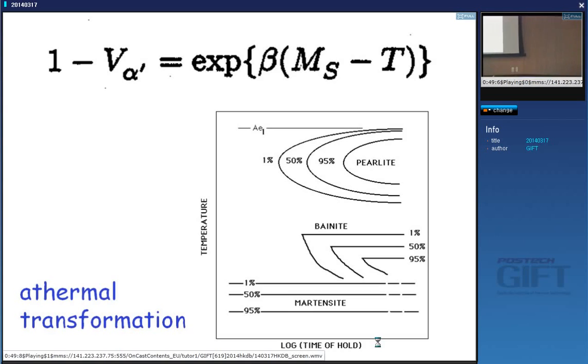There's no diffusion, but there is an interface between the martensite and austenite. So his question is, why shouldn't displacive transformation just happen instantaneously because there's no diffusion? So there's an interface between the austenite and martensite, and that interface has features in it that alter the crystal structure when it moves. Yeah, and those features are called dislocations. I will go into those later. And dislocations have limits to how fast they can move to accomplish the change in crystal structure. So even though it happens fast, it's not limitless.